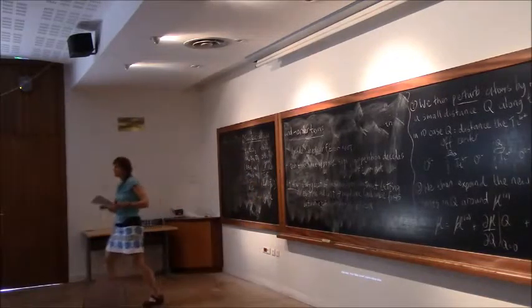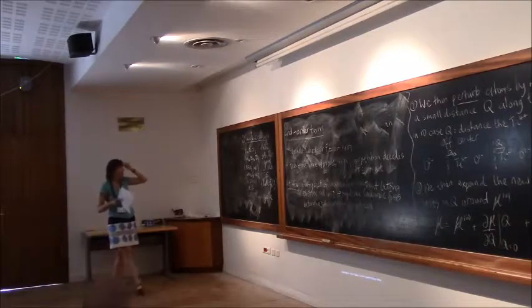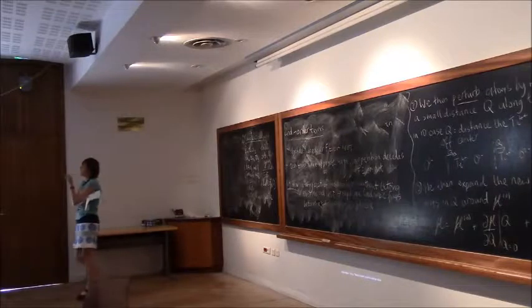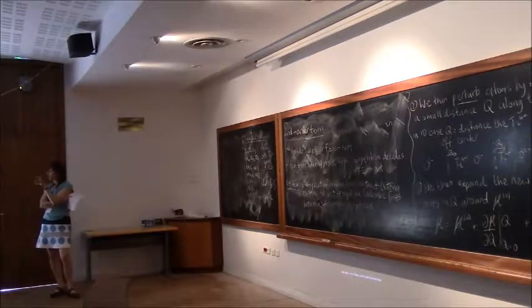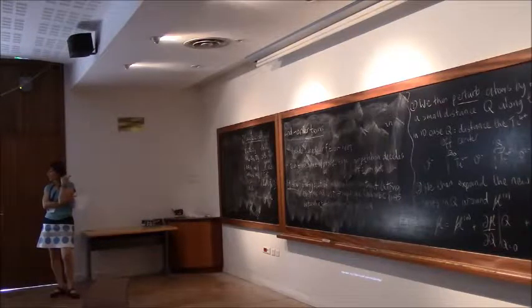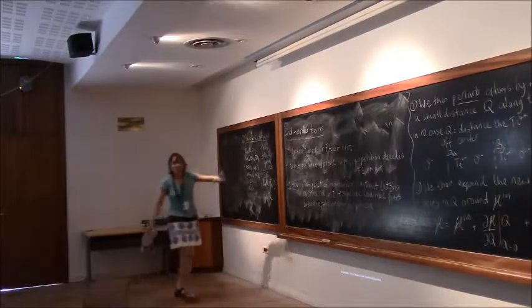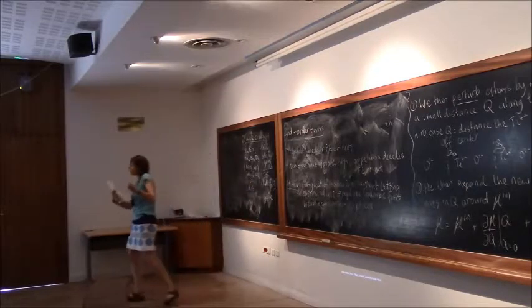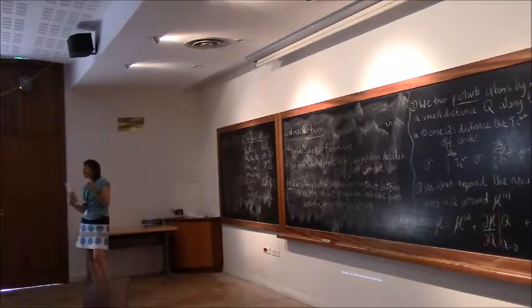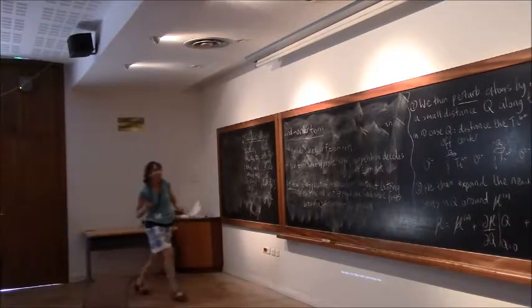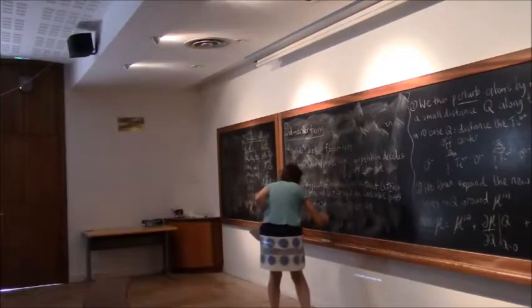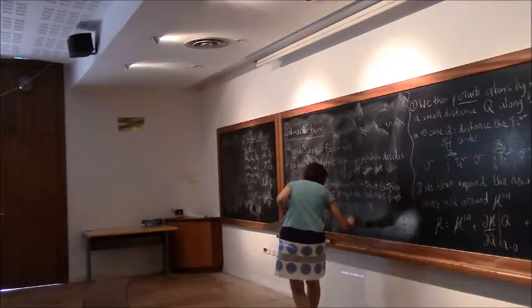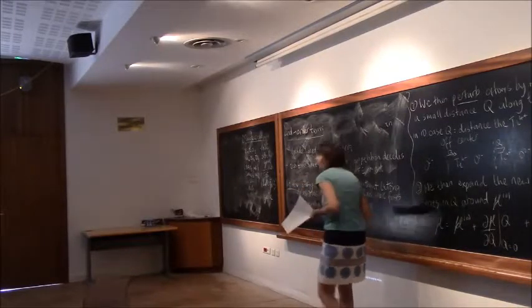Okay, everybody happy conceptually with that? Yep. So immediately I can start to think why these Dn transition metal atoms are not going to be good for ferroelectricity. If I have a lot of valence electrons, then this term is going to be larger. I can minimize this term by having as few electrons as possible in the valence. So for a D0 cation, of course this term will still be positive. There's still an energy cost of pushing a D0 cation towards an oxygen and not letting the electrons adjust. But it's going to be less costly than if I have a lot of valence electrons there. So this term is minimized for few valence electrons. I get less Coulomb repulsion between the electrons and the ions if there are fewer electrons there.